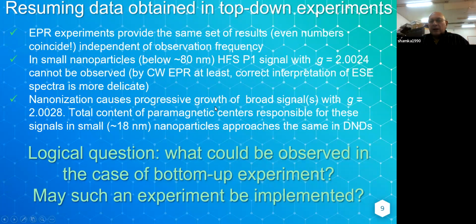Nanonization causes progressive growth of broad signals with G slightly different from this one, and the total content of paramagnetic centers responsible for these signals in small nanoparticles approaches the same as in detonation nanodiamonds, where only these broad signals are observed and the concentration of paramagnetic defects is very, very high.